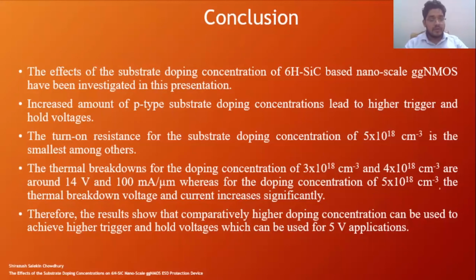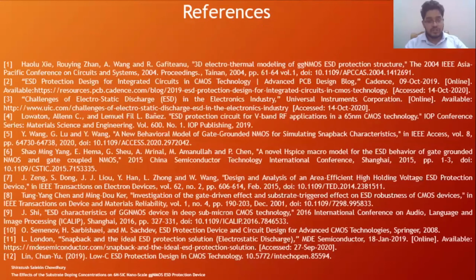The thermal breakdown for the doping concentrations of 3E18 per cm cube and 4E18 per cm cube are around 14 volts and 100 milliampere per micrometer, whereas for the doping concentration of 5E18 per cm cube, the thermal breakdown voltage and current increase significantly. Therefore, the results show that the comparatively higher substrate doping concentration can be used to achieve higher trigger and hold voltage, which can be used for 5 volt applications.